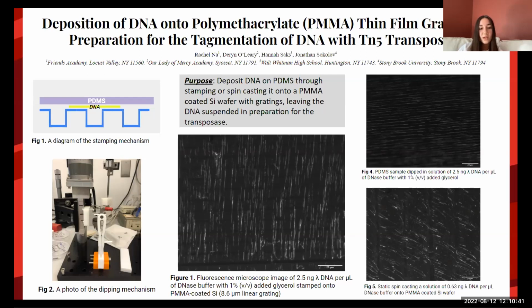The second method we tested was spin casting DNA onto silicon gratings. Static spinning and dynamic spinning were both analyzed. For static spinning, a droplet of DNA solution was placed at the center of the silicon wafer and was incubated for various lengths of time before spinning. For dynamic spinning, a pipette was used to deposit the DNA solution at the edge of the wafer while it was spinning.